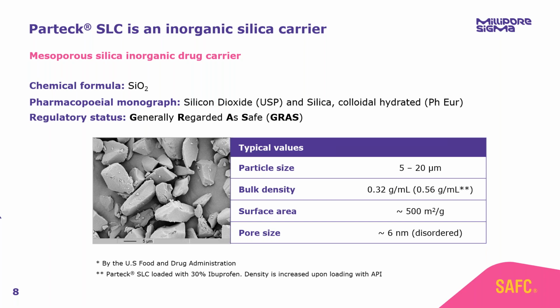And because of that high porosity, our mesoporous silica has a very high surface area. So approximately 500 meters squared per gram. So this is an incredibly high surface area. To put this into perspective, if you were to have a vial with 10 grams of this product, you would have the same accessible surface area in that vial as a standard Premier League football pitch. So a huge amount of accessible surface area.